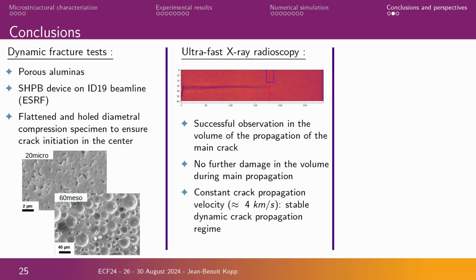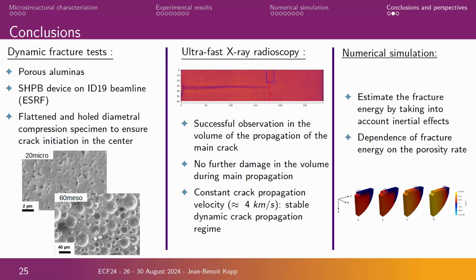So it's quite interesting by using this specific device and by considering the radioscopy. So it was possible to see if we have only one initiation of the crack or if we have a lot of crack propagation at different places in the specimen. So finally, we follow a stable dynamic propagation regime, and it was possible using a numerical simulation to estimate the fracture energy in a dynamic regime by taking into account inertia effects.